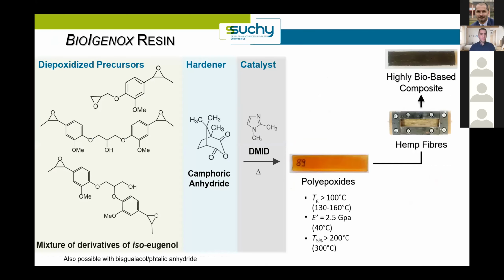So we use the different epoxy prepolymers prepared in Stockholm in curing protocols in the presence of cyclic anhydrides as hardeners. And the most interesting formulations so far have been obtained with isoeugenol derivatives in combination with camphoric anhydride. But we have also achieved promising results with bisguaiacol phthalic anhydride. Glass transition temperatures above 100 degrees were obtained, as well as Young modulus values above 2 gigapascal. And in the case of the isoeugenol derivative, a greener formulation called BioIgenox was developed, leading to a significant reduction in the volumes of organic solvent used.